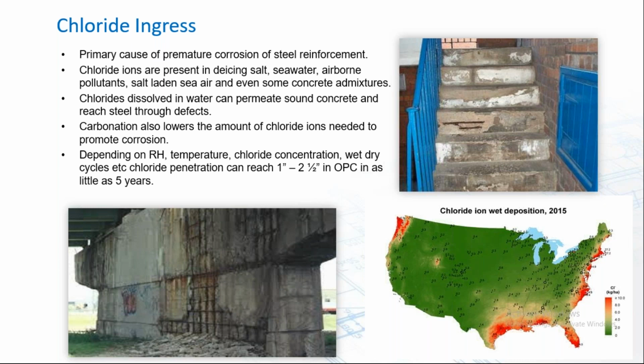Carbonation also lowers the amount of chloride ions needed to promote corrosion. And depending on relative humidity, temperature, chloride concentration, wet and dry cycling, etc., chloride penetration can reach 1 to 2.5 inches into ordinary Portland cement in as little as 5 years. And typically we're talking about only a 2-inch cover on reinforcing. So you can see how aggressive this can be in really creating a problem for concrete structures.